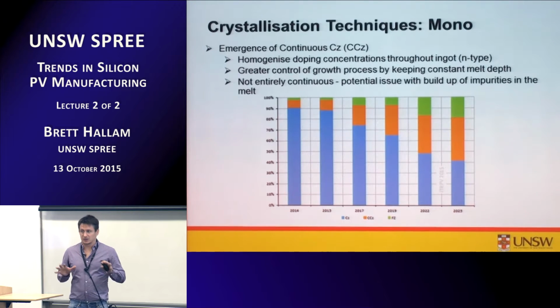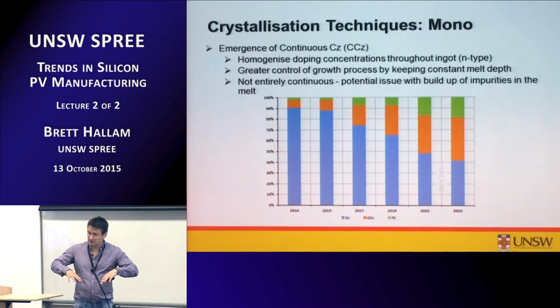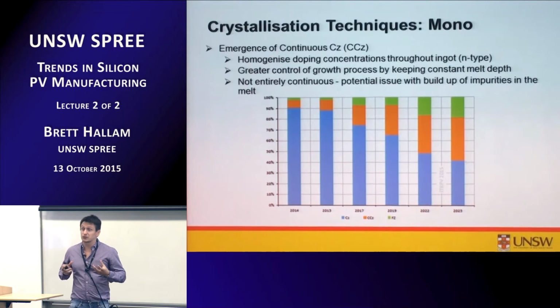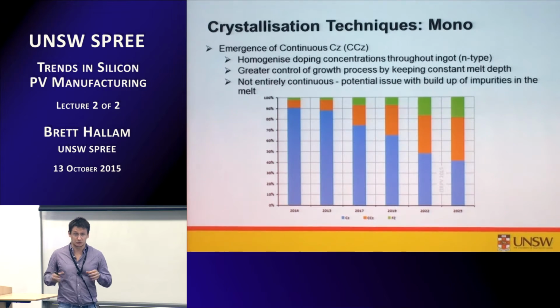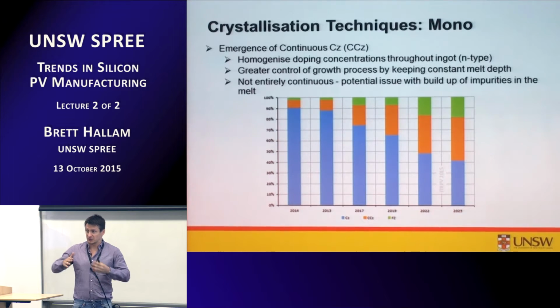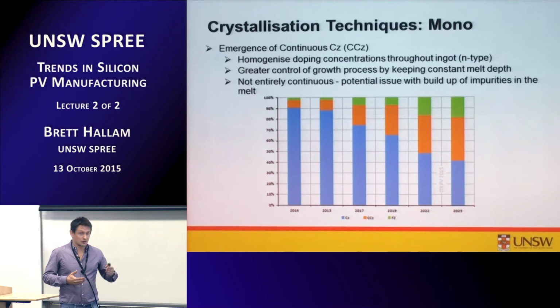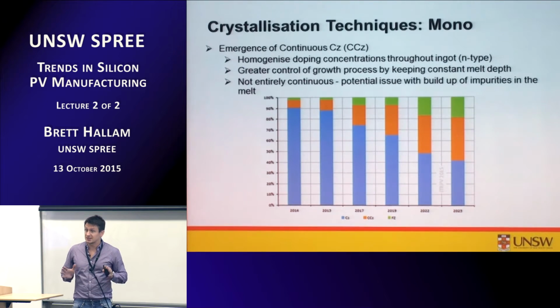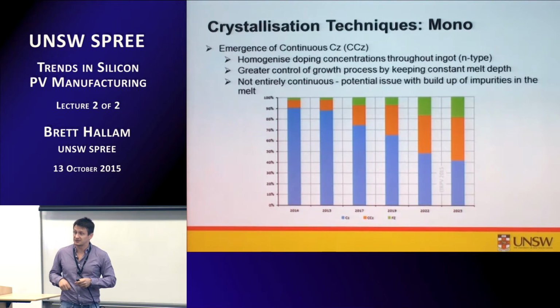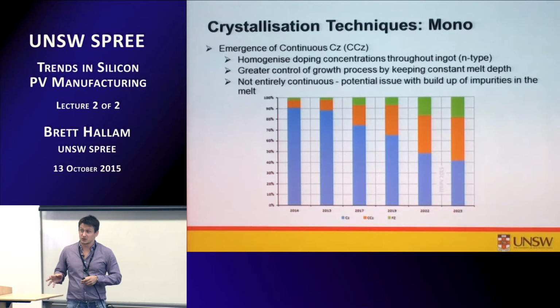The impurities during the monocrystalline silicon process segregate out into the melt. So it's sort of like a relatively good purification process for minimizing metal incorporation into the silicon. So iron, for example, for every silicon atom, only 1/1,000,000th of an iron atom will incorporate into the actual crystal. So that's great at the start of the ingot, but as you continue to grow the ingot, the impurities do build up, so you'll get relatively higher impurity concentrations, typically towards the last part of the ingot to solidify. Unfortunately, that also works for the dopants.